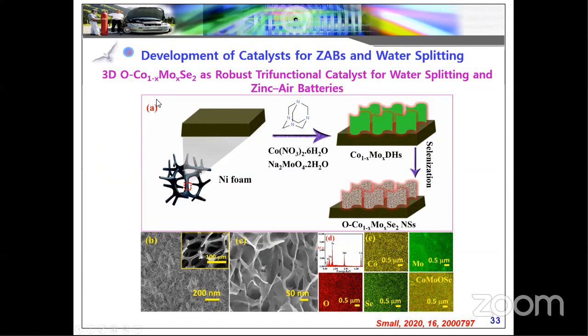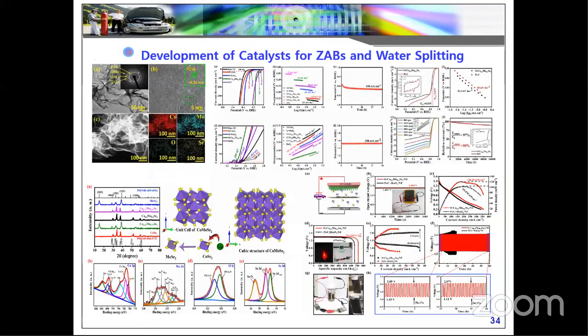We have developed cobalt molybdenum selenide materials, and the material should be oxygen dominated, because that is one of the challenging issues. When you increase the oxygen vacancy, or develop an oxygen dominated material, that material should have long-term durability and high adsorption ability towards the OER and ORR properties. And we also performed different morphological and structural analyses. And finally, the HER, OER and ORR performances. From these studies, the material is trifunctional, and finally we fabricated the device and tested different electrochemical performances. From these performances, we conclude our catalyst is one of the best catalysts.